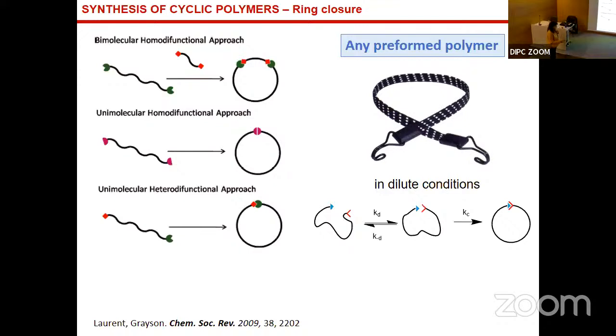We have a linear polymer. We can synthesize any linear polymer with any composition. We modify, for example, the end groups, and we can form the cyclic polymers by combining with a linker, or by making the reaction between the ends of the polymer. It can be the same group, different group.